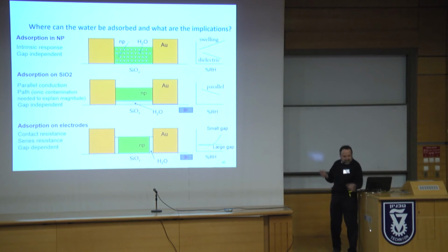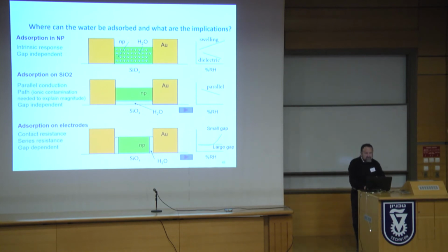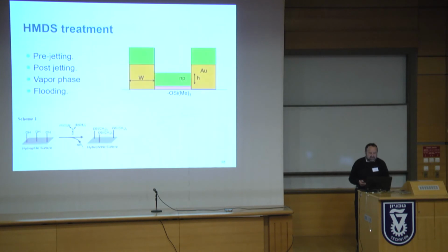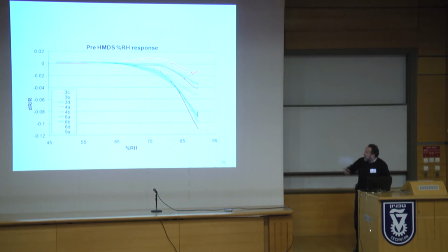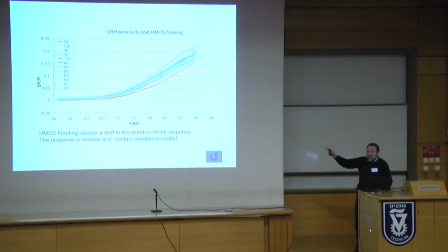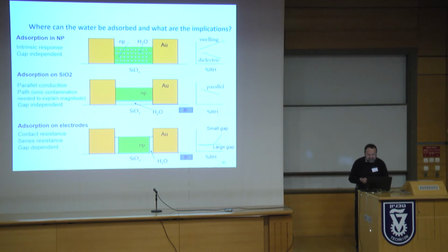So, in order to eliminate the effect of the SiO2, we actually treated it with HMDS, by eliminating the parallel path. And what we saw, this was before, and this was after. All the negative effect of all the electrodes of the sensing disappeared, and everything now goes up, because probably this is the intrinsic response and the contact response also. I know it's a bit difficult, but I hope I can convey this picture.